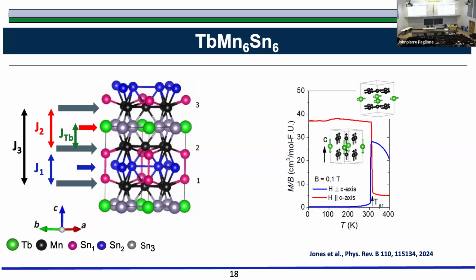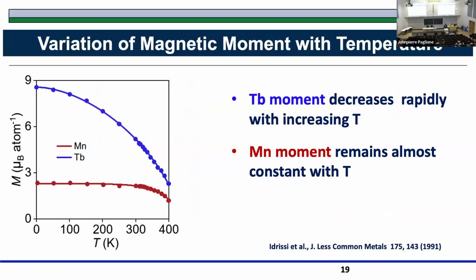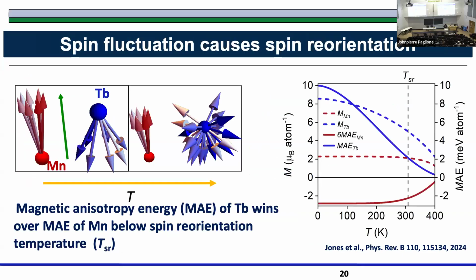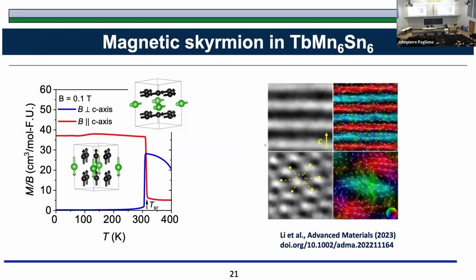And I'll tell you that a very interesting feature has been realized in the region where the spin reorientation happens. Actually, I will skip this, because we were able to explain that the two-dimensional nature of the magnetic ordering enhances the fluctuations, and those fluctuations play a role in this spin reorientation. But what I will show you is that right here in this region, these skyrmionic textures were discovered. This was not our work, it was some other groups' work. But in one of these R166 systems, we have been able to engineer this skyrmionic texture that has yet to come. We published it, so I didn't put it into this talk, but it's very interesting.